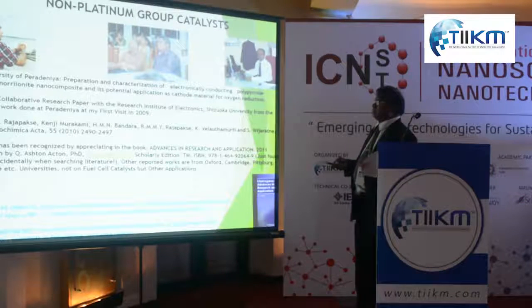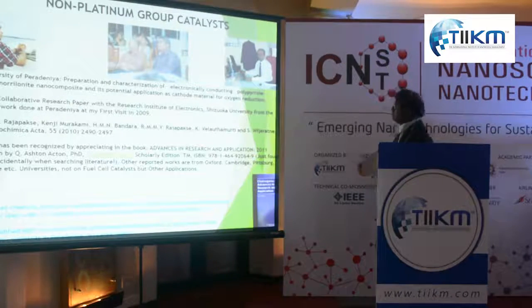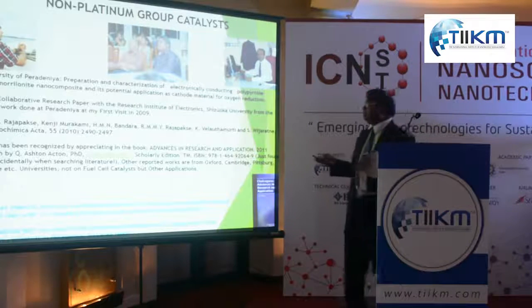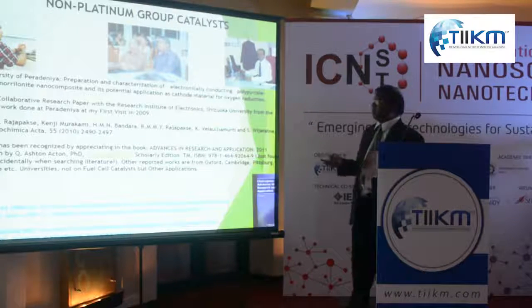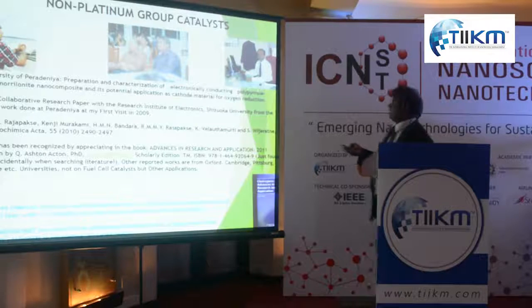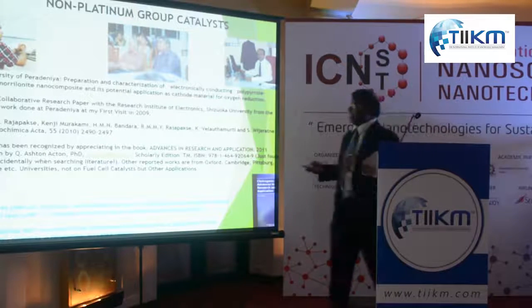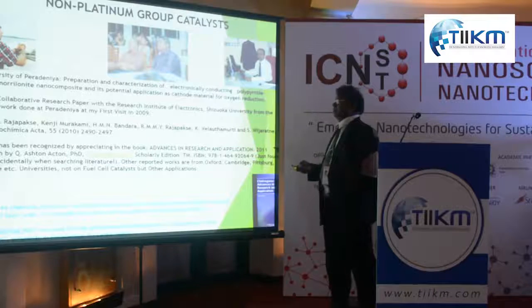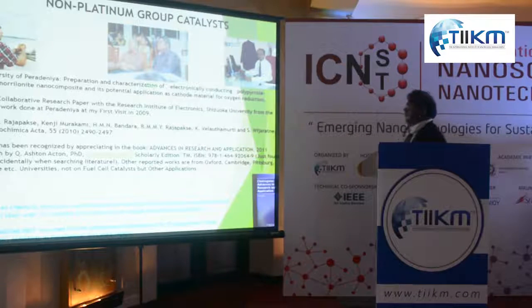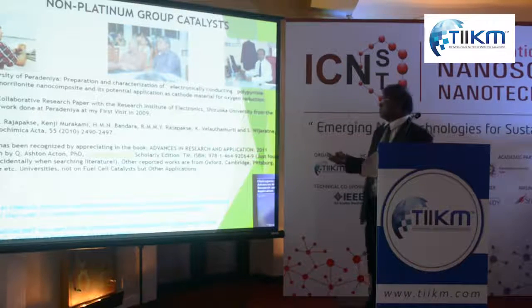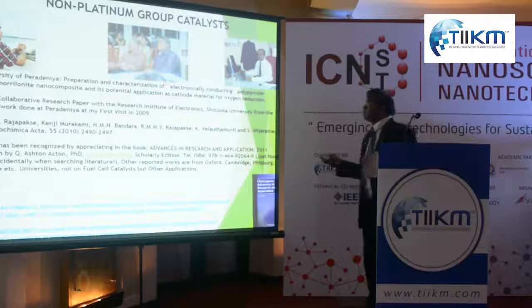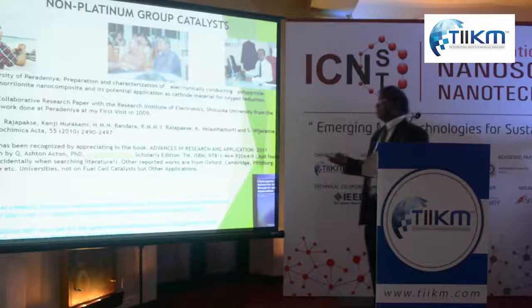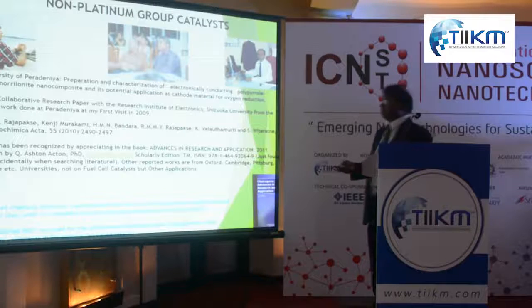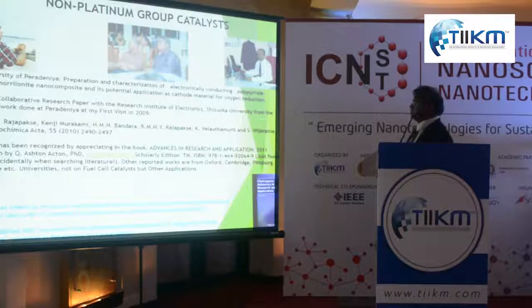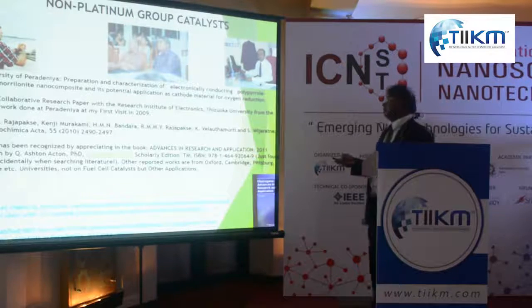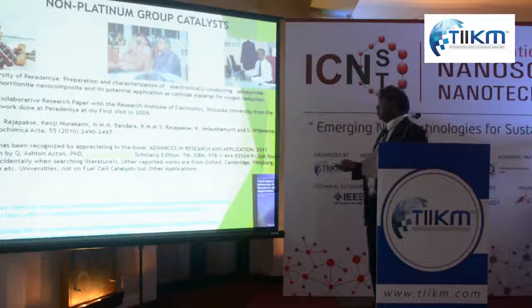And in our university, we were the first to use very cheap and mundane materials like polypyrrole, an electronically conducting polymer, and montmorillonite clay nanocomposite. So we found that this nanocomposite is a very good oxygen reduction catalyst. So you can use it as cathode material in fuel cells. After this discovery we collaborated with Shizuoka University in Japan.